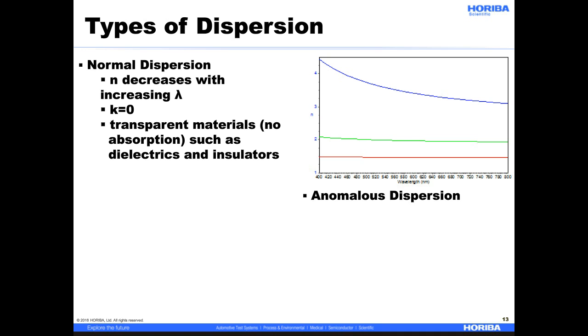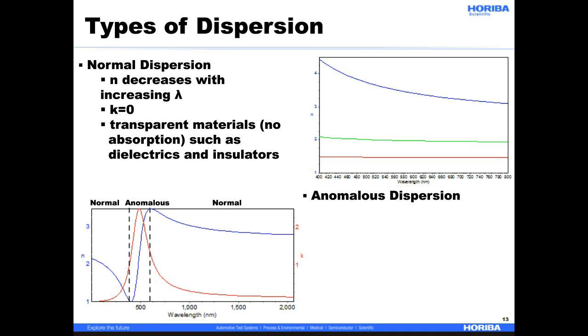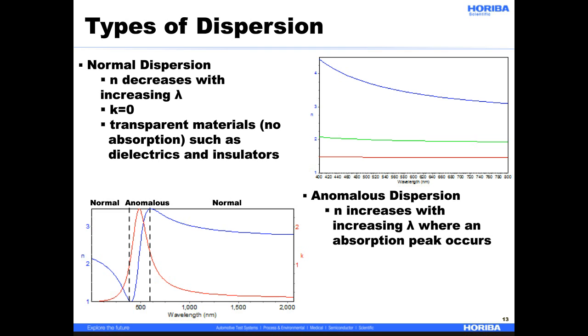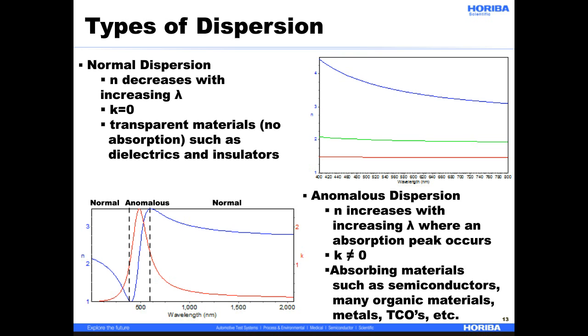The other type would be anomalous dispersion. For anomalous dispersion, n increases with increasing lambda where an absorption peak occurs, and k is, of course, not equal to 0. This is dispersion that is used for absorbing materials, such as semiconductors, many of the organic materials we'll talk about today, and transparent conducting oxides, etc.